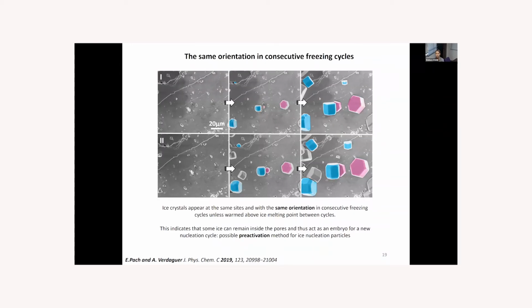And also very important was to see that the ice crystals appeared at the same sites and with the same orientation in consecutive freezing cycles, unless they were warmed above the melting point, then it changed. This may indicate that ice can remain inside the pores and thus act as an embryo for a new nucleation cycle. This could be seen as a possible pre-activation method for ice nucleation particles.